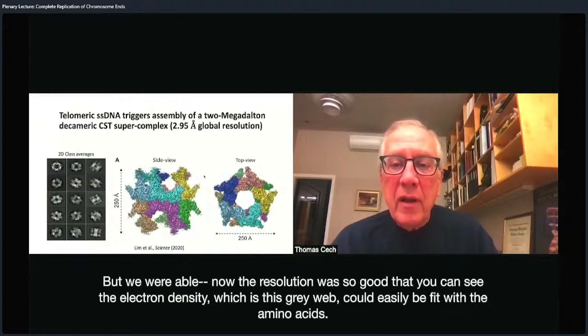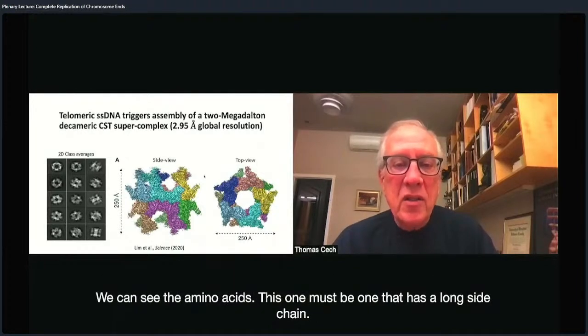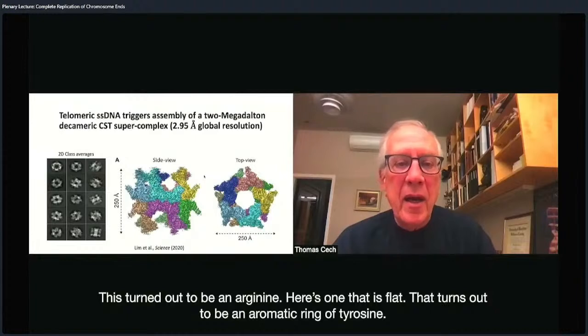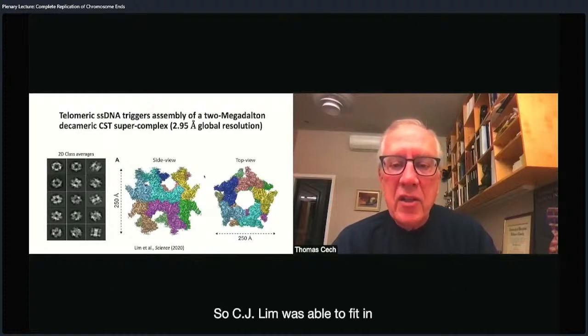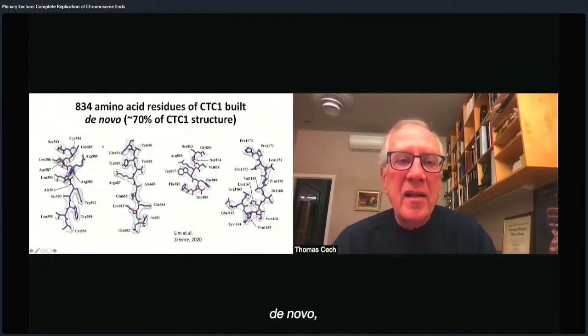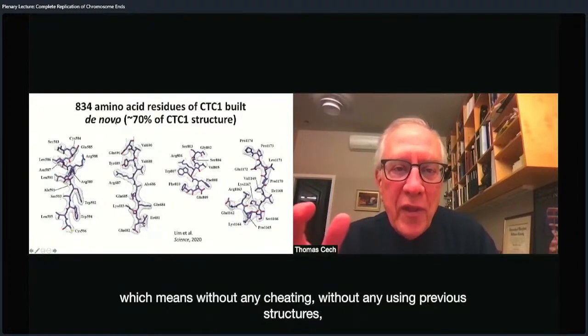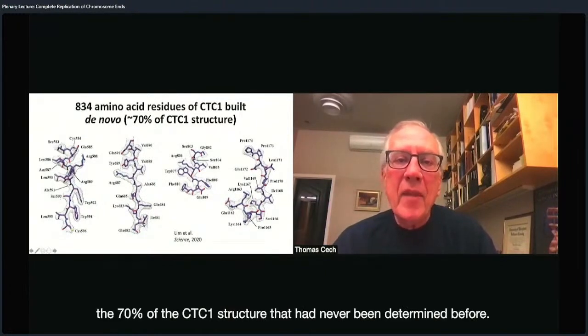But the resolution was so good that you can see that the electron density, which is this gray web, could easily be fit with the amino acids. We can see the amino acids. This one must be one that has a long side chain. This turned out to be an arginine. Here's one that is flat. That turns out to be an aromatic ring of a tyrosine. So C.J. Lim was able to fit in de novo, which means without any cheating, without using previous structures, 70% of the CTC1 structure that had never been determined before.